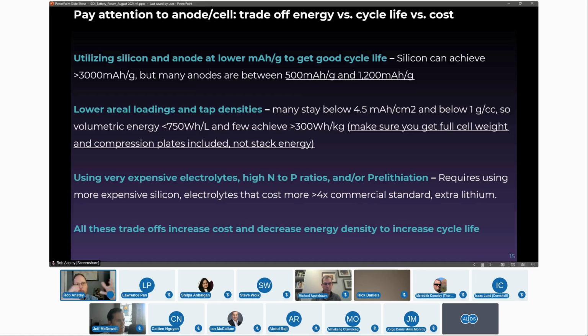And that's why most of the commercial cells we're looking at are really only running their anode around 600 milliamp hours per gram. And they're not going to super high areal loadings. They're staying below 4.5 milliamp hours per centimeter squared. They're staying below 1 gram per cubic centimeter density so that the silicon has room to expand and contract. And that's why most of them in commercial cells are below 750, but some are above 300 watt hours per kilogram, because they're giving up all that volumetric energy by doing a low rating, a low density, and a low loading.